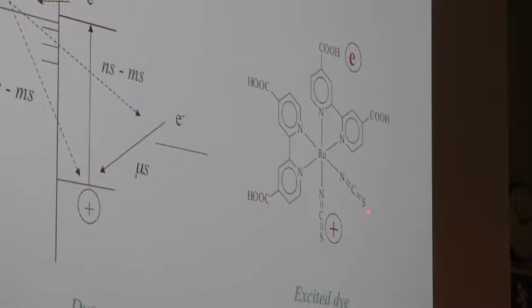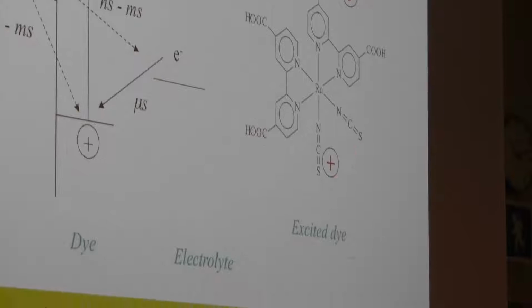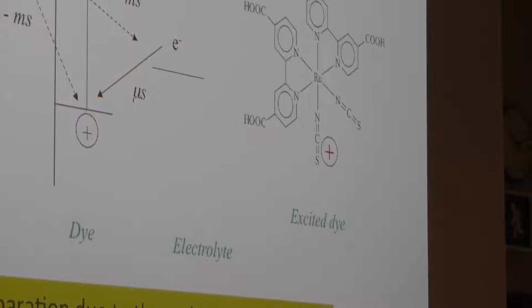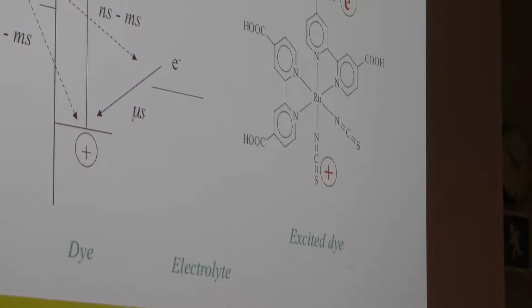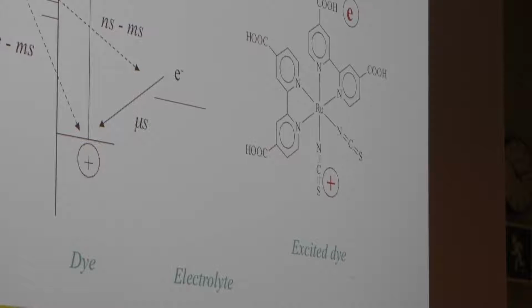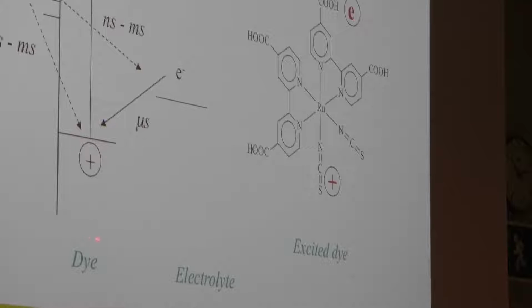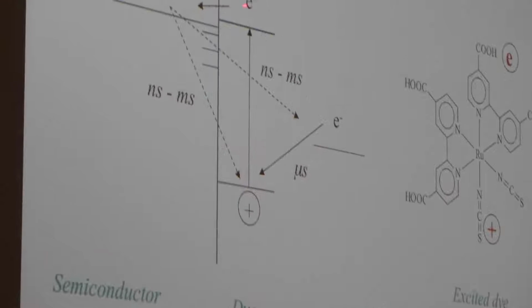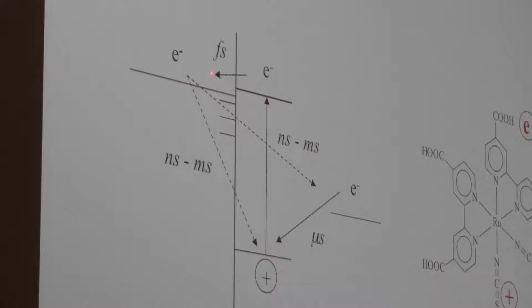The hole, on the other hand, is mostly located on the sulfur. So by this principle we can understand that when you excite, the electron goes to the TiO2 and the hole goes to the electrolyte side. So we can really separate the electron and hole by the dye design itself. And the kinetics is then very favorable. You inject very, very fast, on the femtosecond time scale for the best dyes, let's say.